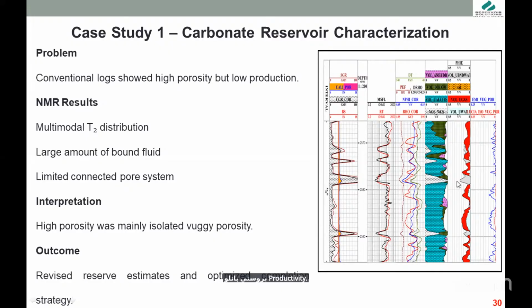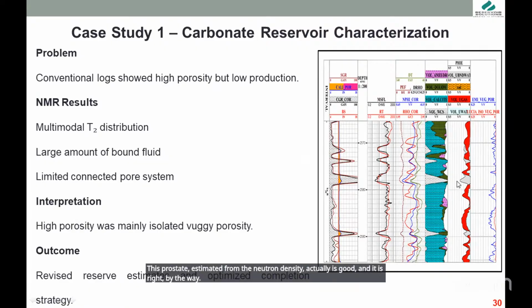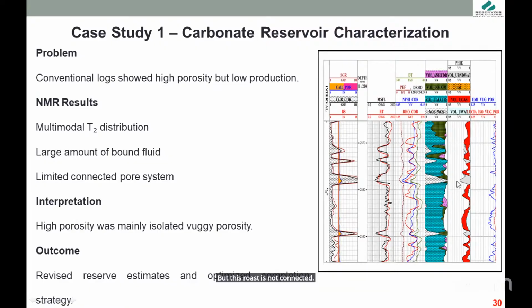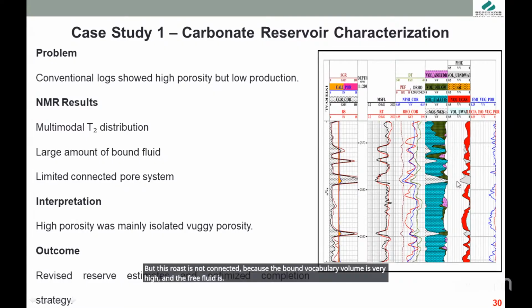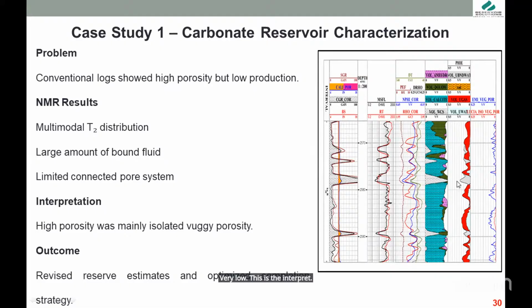Limited connected pore system. As you found here, this is not connected. It's more or less the same as the example we gave in the carbonate characterization. Interpretation: high porosity with mainly isolated vuggy porosity. This porosity estimated from the neutron density actually is good, and it is right, by the way, but this porosity is not connected because the bound capillary volume is very high and the free fluid is very low. This is the interpretation coming from the NMR result.